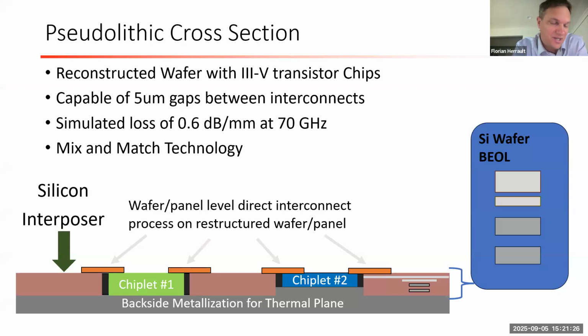So this is a cartoon. We do have cross-section images, but I didn't use them here. Effectively, the pseudolithic process is a reconstructed wafer with embedded III-V transistor chiplets in the silicon. We start by taking our silicon wafers from our foundry and etching through-substrate vias or through-substrate cavities all the way from top to bottom, creating effectively a Swiss cheese wafer, if you will, with pockets into which we embed our chiplets using a dielectric sidewall bonding process. It's represented on this cartoon with the black area.